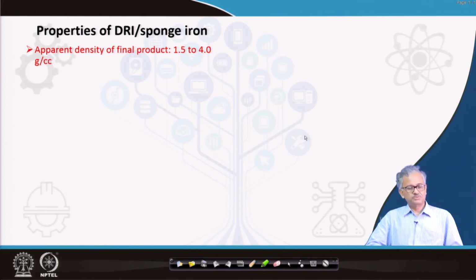Properties of DRI and sponge iron. First you must know some of the properties of the sponge iron. The apparent density of the final product is around 1.5 to 4 gram per cc. You know the iron density is around 7 to 8 gram per cc. Compared to this, the apparent density of the sponge iron is so much less, 1.5 to 4. Why? Basically, the sponge iron obviously contains some gangue, and gangue contains a lot of oxygen. And then also, depending on the metallization, FeO will be there in the system.